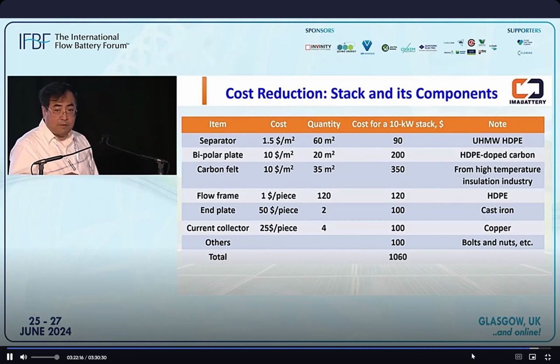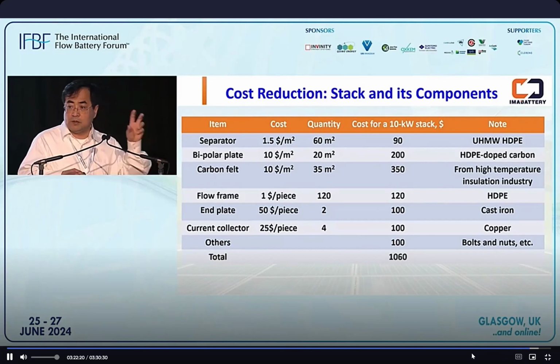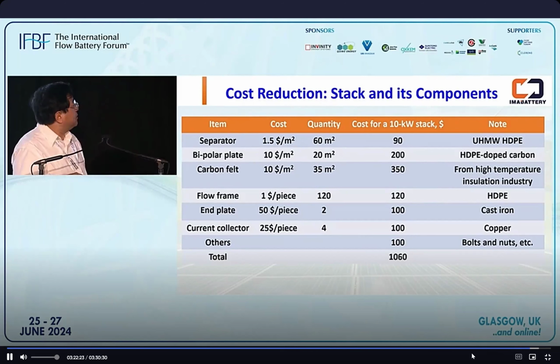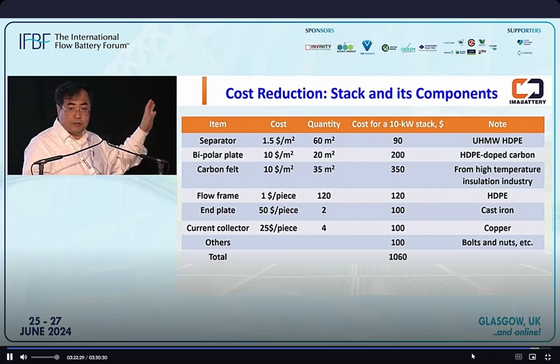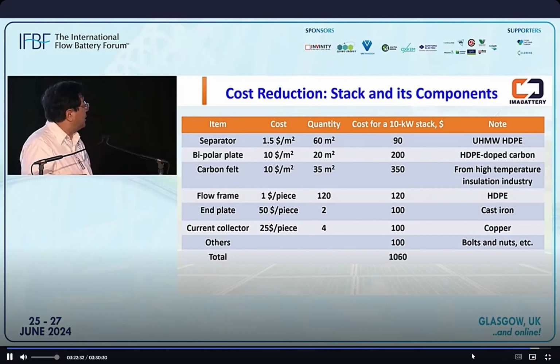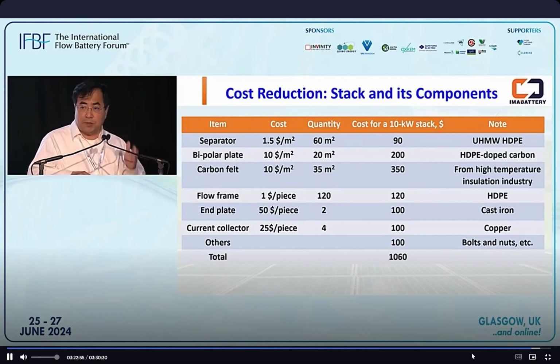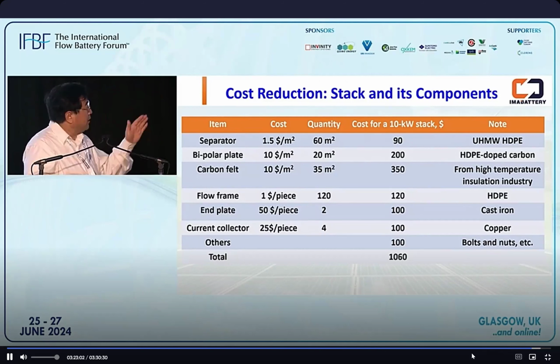Carbon felt, this is not graphite felt, because I use iron 2 and iron 3, so the oxidation voltage is too low, so we can survive with carbon fiber. From the high temperature insulation industry, this price is very reasonable. And the current collector is copper. Based on Adam's talk today, I think I can reduce this cost, maybe cut it by half. So in terms of material cost for a stack with 10 kilowatt standard rated power, the total cost is about $1,000. Which means $100 per kilowatt, and for a 10-hour system, that's $10 per kilowatt hour. So that's the material cost.